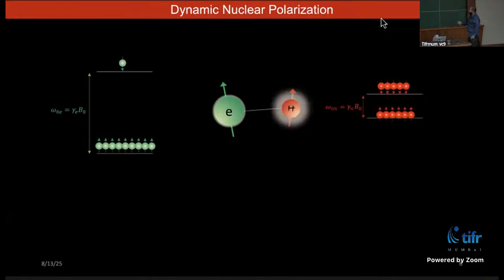So the idea of this technique, dynamic nuclear polarization, is to transfer this large polarization from electron spin to nuclear spin. And of course, if you want to do a transfer between two different spins, they have to be coupled. If we have a scenario where electron spin and nuclear spin are coupled, it's possible to transfer the sensitivity of the electron spin to the nuclear spin.